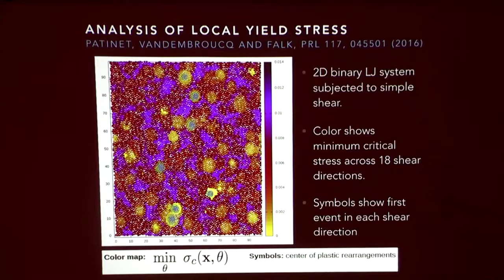What Sylvain can do is athermal quasi-static shear again, so not dynamics, zero temperature, essentially energy minimization shear, and look to see in different orientations what is the first place that deforms in this material. The teal circles correlate quite well with the yellow circles where the yield stress is low. I'll show quantitative data on this in a moment. So this is like a brute force measurement of the local yield stress.